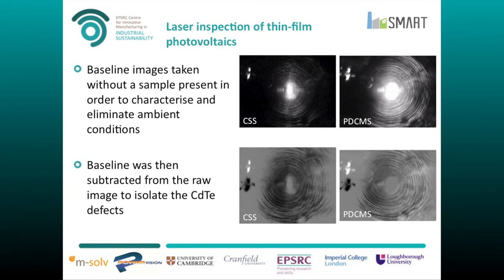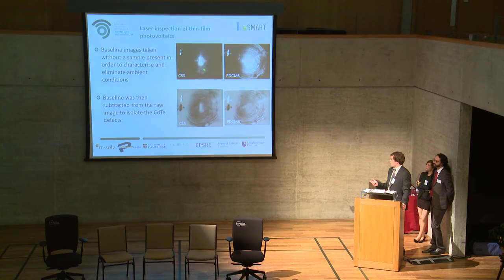Well, what we do is we create baseline images. So we shine the laser into the camera in place without having a cadmium telluride sample in place. And that gives us all of the data from all of the ambient diffraction sources, and we get baseline images. We then subtract the baseline image from the raw image of the cadmium telluride to create a combined image which subtracts the baseline from the cadmium telluride and shows us just the cadmium telluride. So this is the image as it looks like when you shine a laser through a panel into a camera, and this is what it looks like after we've subtracted the baseline.